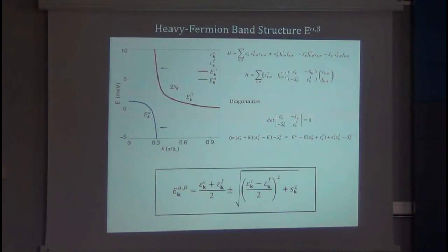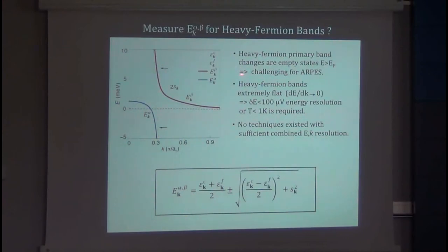But amazingly, people had not actually measured the existence of these bands by momentum space techniques over all those decades. And I'll tell you why. First of all, these bands, this is 5 millivolts. This is 0 millivolts. So this band here, above the chemical potential, is maybe 1 millivolt wide. It's not like a regular solid state band, which is 10 electron volts wide. It's an extremely narrow band, which is only 1 or 2 millivolts wide. And similarly for this one.